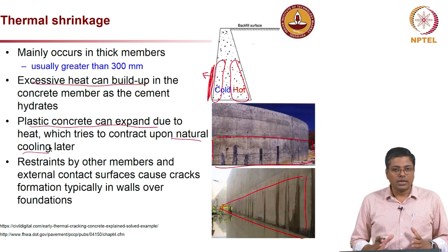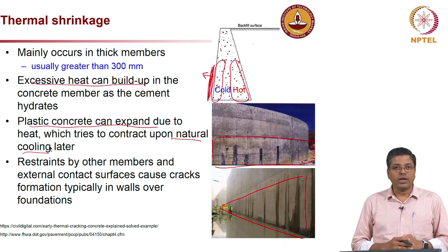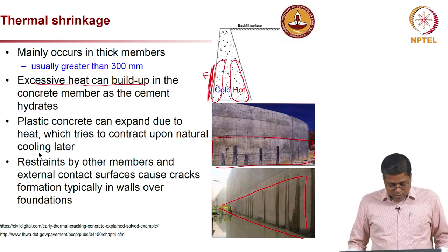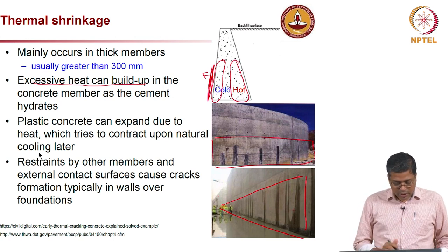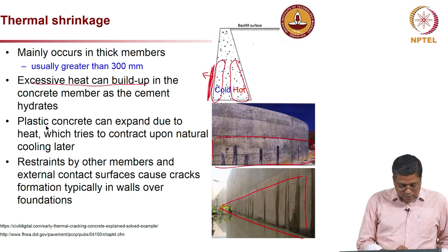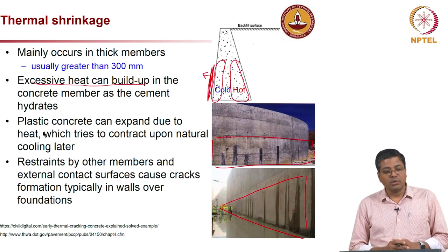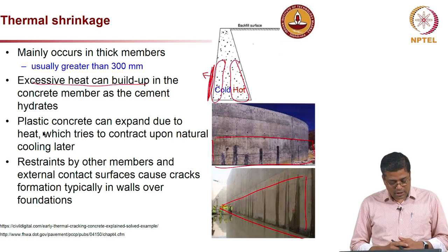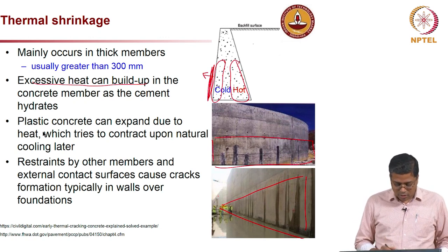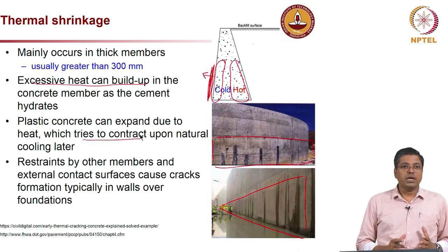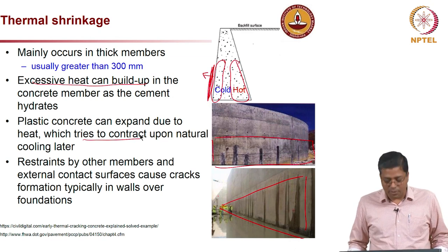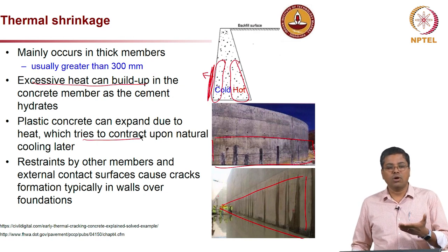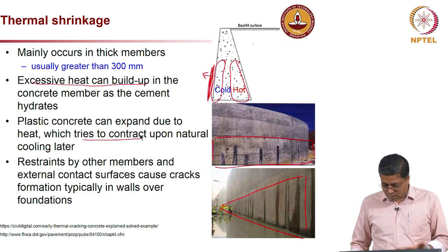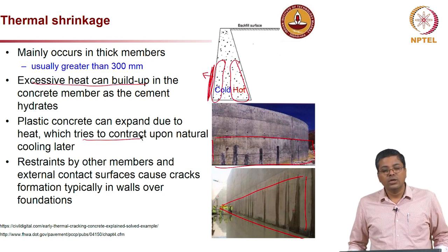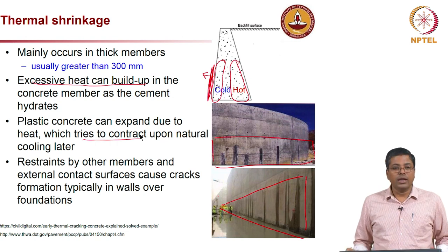Now, it is not necessary that it happens uniformly everywhere on the structure. Before I go to the next slide, let me explain at what time and why this kind of crack happens. One thing is excessive heat, which we already discussed. The other thing is that the plastic concrete expands due to the high heat generation in the beginning, and as the concrete cools down, it tries to contract or shrink. And because there is restraint, in other words it is not free shrinkage, there is reinforcement in the concrete, and the concrete is also resting on earth or some foundation, and on the other side the backfill is there. So there is a lot of restraint provided by the surrounding elements.